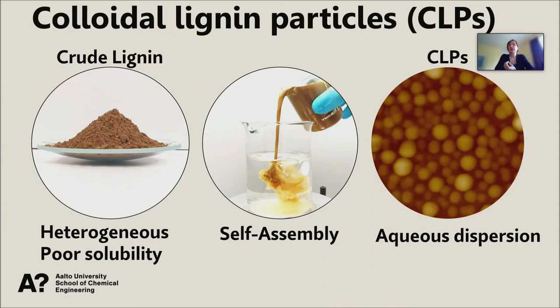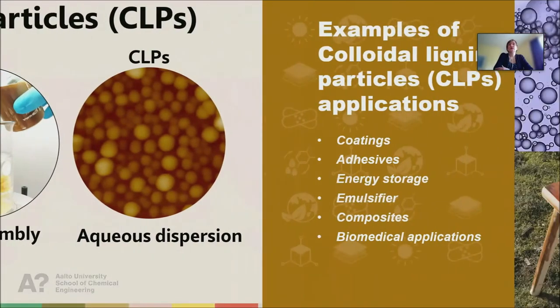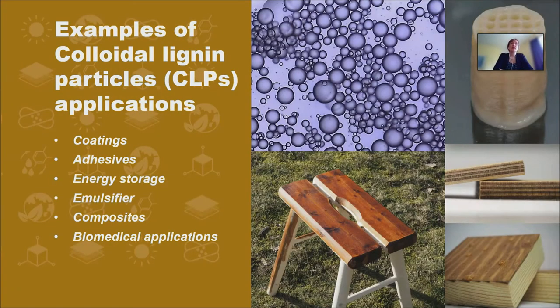And then we have an aqueous dispersion of the spherical particles. This is much easier to disperse, either as dry or to use as wet. So the idea is that we can increase the possible uses of lignin by producing these lignin particles. And this self-assembly or nanoprecipitation method is scalable and very simple. I will show you a few examples of the applications that we can use the lignin particles for.